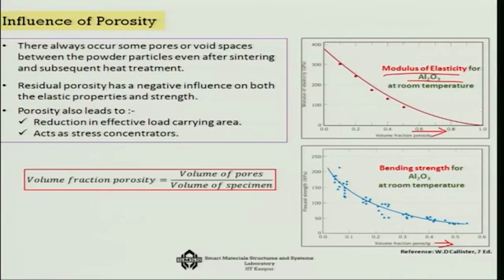Of course, one interesting thing is that, unlike the modulus of elasticity, the strengths are not on a single line; you can see that they are more distributed. That is what I will be talking about later, that this distribution is probability related, and that is why there is a Weibull modulus related to the whole thing. Now, the volume fraction of porosity plays a very important role, which is the volume of pores over the volume of the specimen. So, the higher the volume fraction, the more degradation you expect in the material properties, particularly the strength of the system.